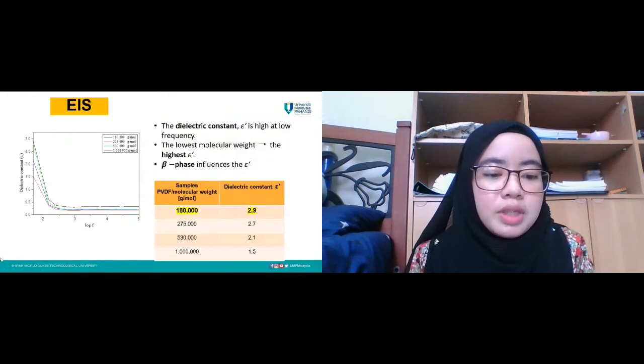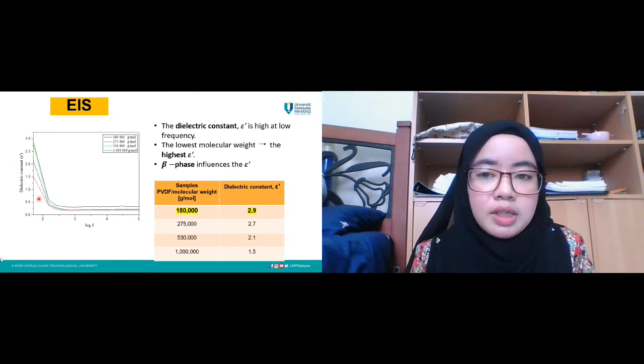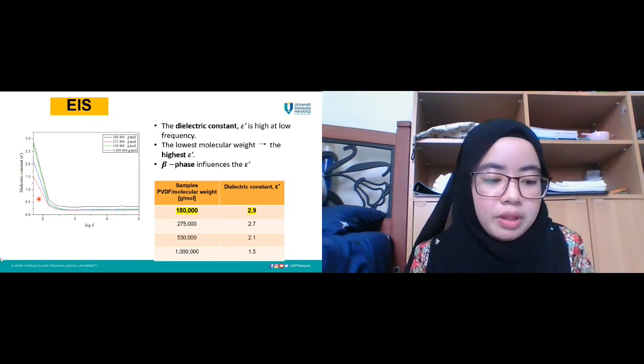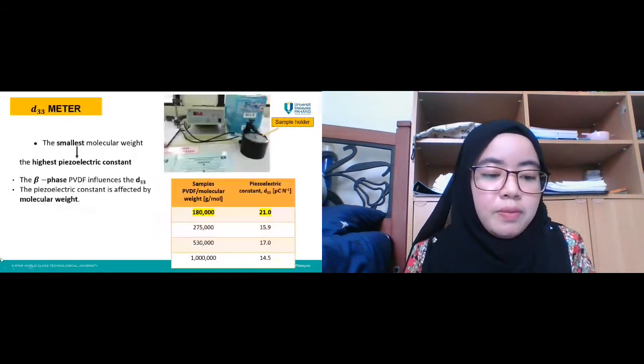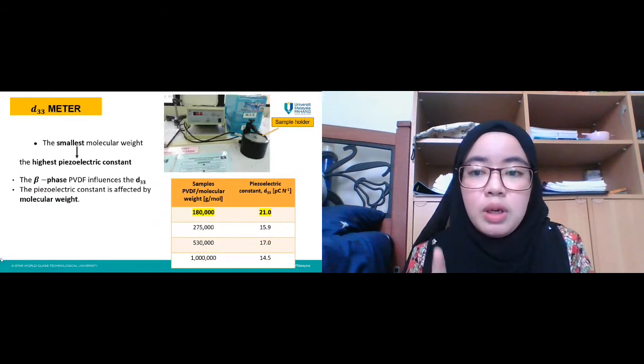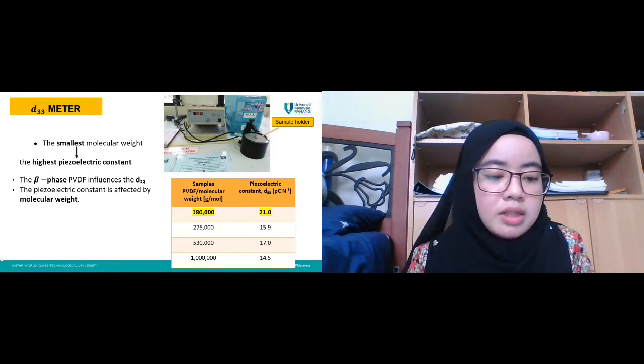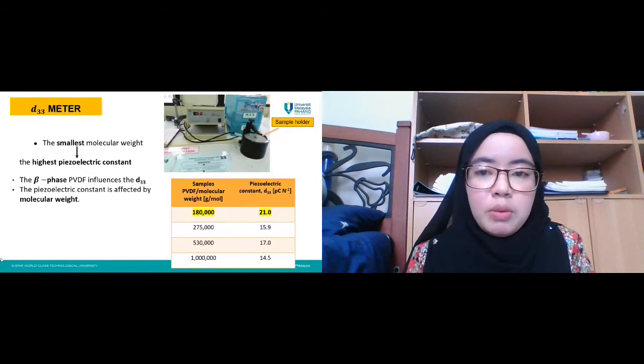Next, to study the effect of molecular weight, the electrical properties of the membrane were evaluated by EIS and D33. The lowest molecular weight has the highest dielectric constant, which is 2.9, because it has high beta phase content. Same goes for the piezoelectric constant. The lowest molecular weight has the highest piezoelectric constant, which is 21.0 picocoulomb per newton. Thus, piezoelectric constant and dielectric constant are affected by molecular weight.